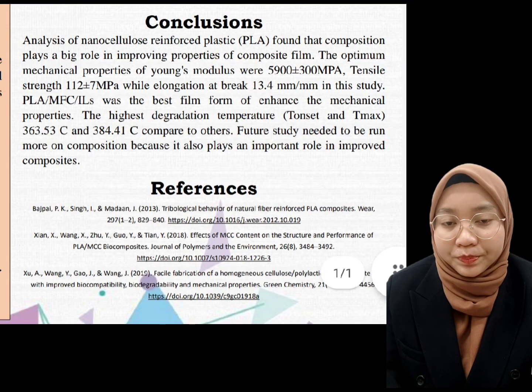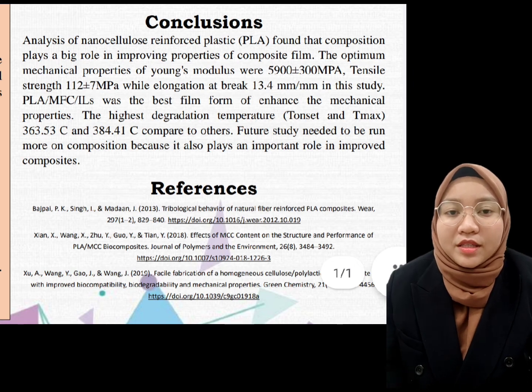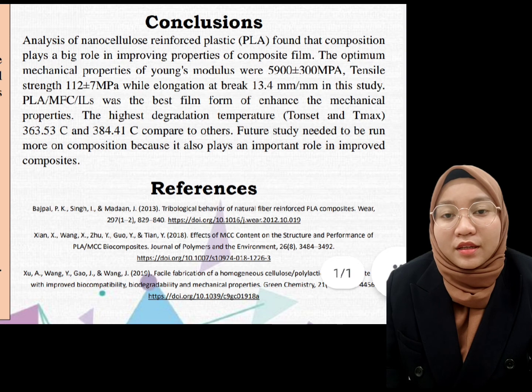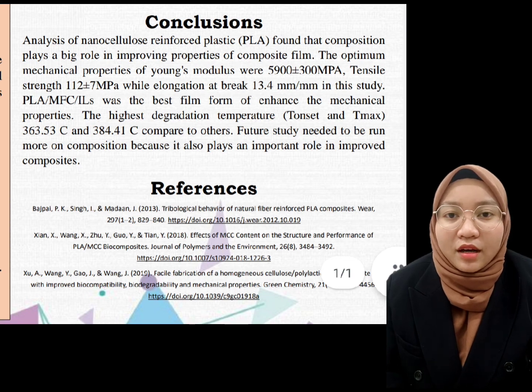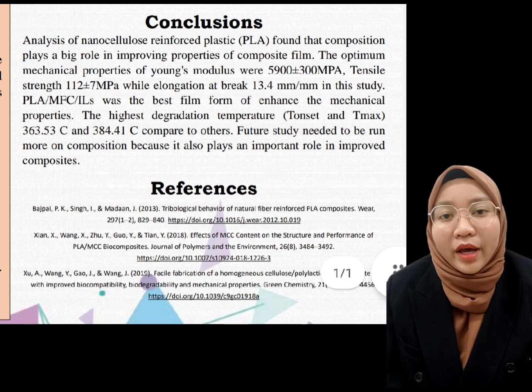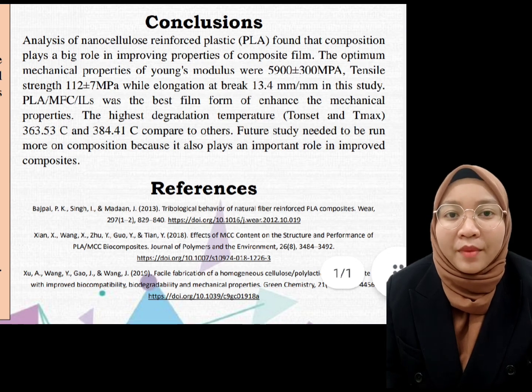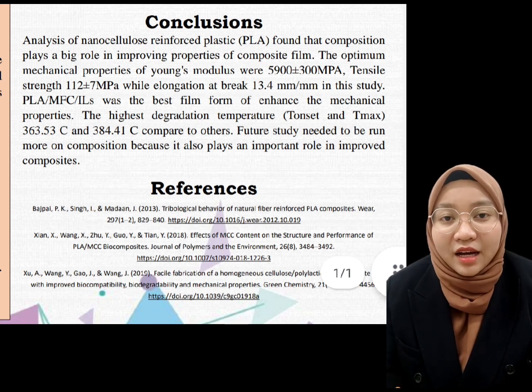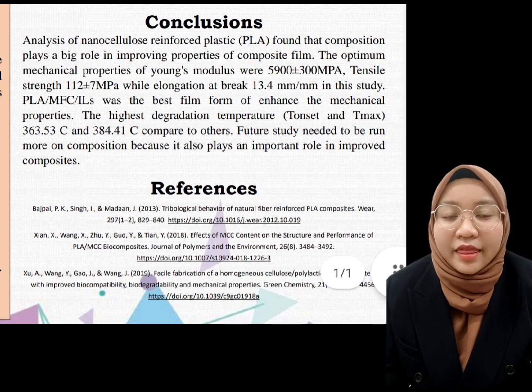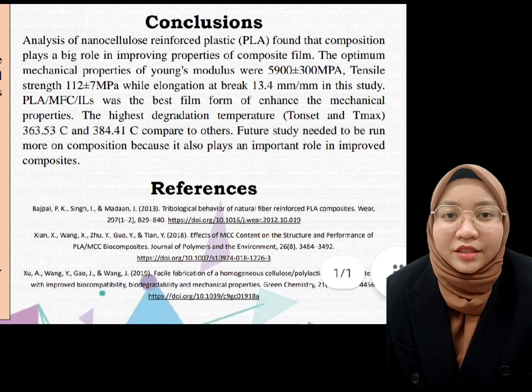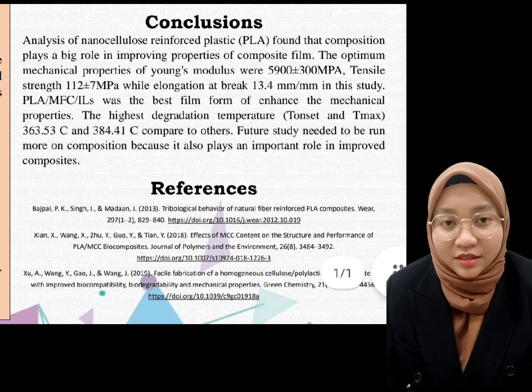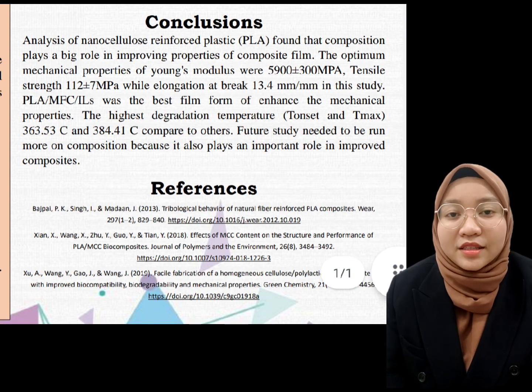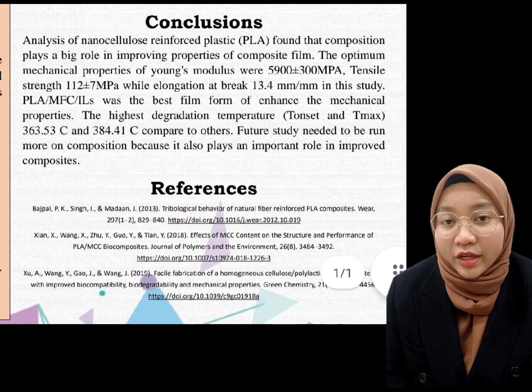In conclusion, the optimal mechanical properties of Young modulus were 5900 plus minus 300 MPa. Tensile strength is 112 plus minus 7 MPa, while elongation at break is 13.4 mm per mm in this study. PLA, MFC or ILs was the best film form to enhance the mechanical properties. However, the highest degradation temperature, the onset and the maximum, is 363.53 Celsius and 384.41 Celsius compared to others.